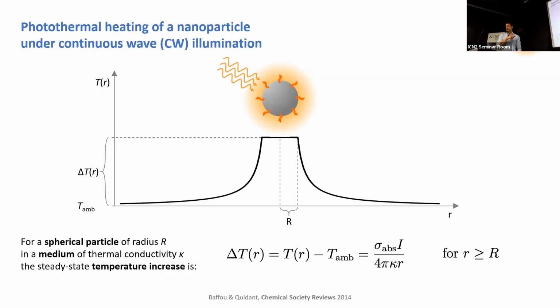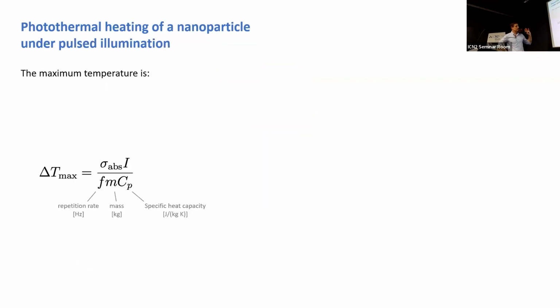And so the first example that I'm going to show you is precisely exploiting this temperature gradient in activating chemistry locally at the nanoscale. The second example, however, has to do not with CW illumination, but with pulse illumination. And in pulse illumination, you have a pulse of light, and then after a certain amount of time, which is determined by the repetition rate of your laser, you have another pulse of light. Now, in this case, we cannot define a steady state temperature. We cannot say the nanoparticle is always a certain delta T hotter than the environment, because as soon as the pulse arrives, it heats up and then it cools down on the order of nanoseconds. That's the cooling rate. And then maybe another pulse is coming, the temperature goes up and then it cools down, and then another pulse is coming and so forth.